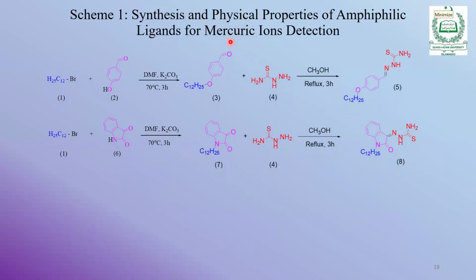The first part of the synthesis: the amphiphilic ligands for mercury ions. As we are targeting the mercury ions, we are going to synthesize the amphiphilic ligands which can selectively attach with the mercury ions. So we took two bromides. You see this is a C12 chain bromide, C12H25Br. In one scheme we use a simple hydroxybenzaldehyde, in the other we used another carbonyl compound, isatin. So this is O-alkylation, and here also this is N-alkylation.